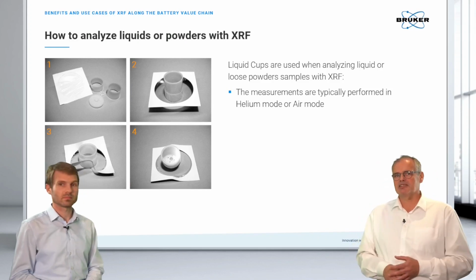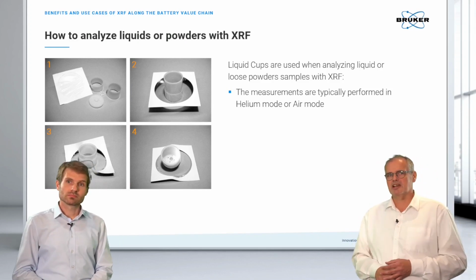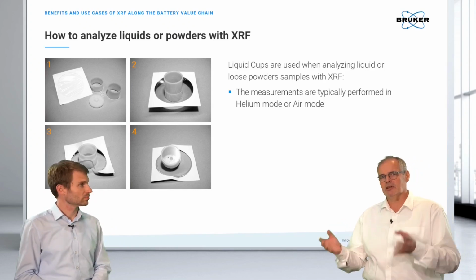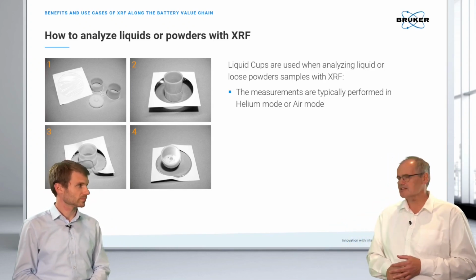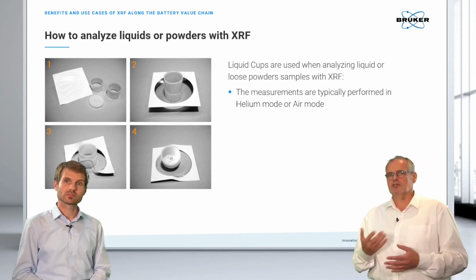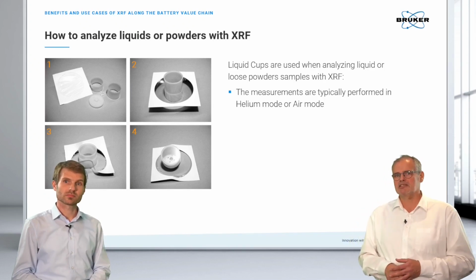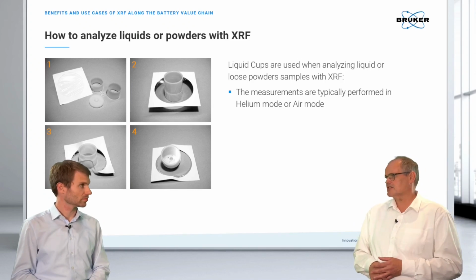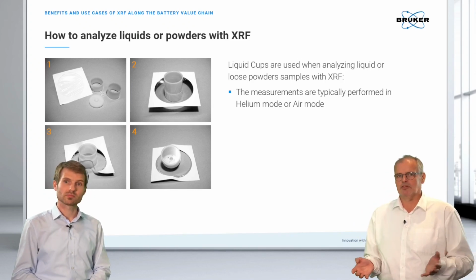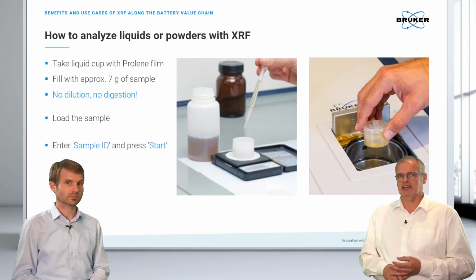Typically, those samples can be analyzed in helium mode for very light elements like sodium and magnesium. When you look for medium or heavy elements like nickel, manganese, cobalt, we can use the air mode, and the intensity is high enough.